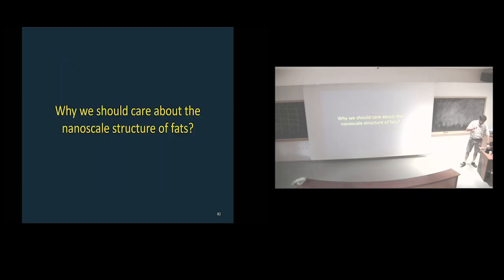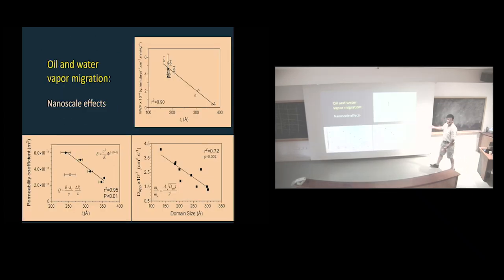And we found that it was correlated. I mean, who gives a hoot? You know, it was related to all kinds of things. Water vapor permeability, when you have a fat film and you want to prevent water from going through, is highly related to the domain size. What about oil migration through chocolate? There's a permeability coefficient related to the domain size in angstroms.